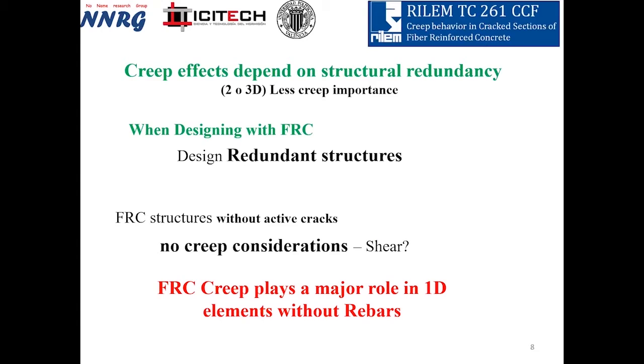Then thinking on big redundant structures, the creep effect will be diffused into the redistribution of stresses. The real problem is when you work in a 1D element without rebar. Even for the other effects like shear, usually we work with sections where you never have cracks in service. It's clear that creep is a phenomenon that we need to consider in service conditions.